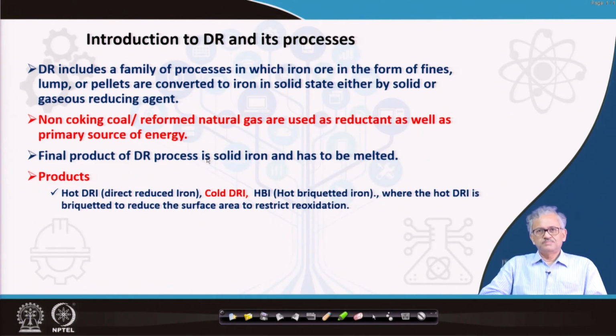Or what you can do, you can cool this DRI and store it, and then transport it, or sell it to other places where they want to use it. That is called the cold DRI. Cold DRI, what is that? It is hot DRI that you cool, because you do not have provision for charging it to the electric arc furnace directly. At high temperature you cannot keep the DRI, as it will be very prone to reoxidation. So you have to cool it in an inert atmosphere to room temperature, and you can store it for a long time, because its propensity for reoxidation is less at room temperature. Also, you can passivate the DRI before you cool it. That is called the cold DRI, and then you use it whenever required.